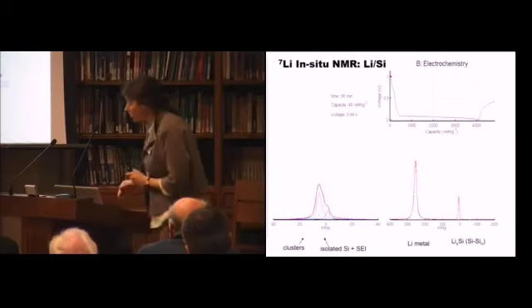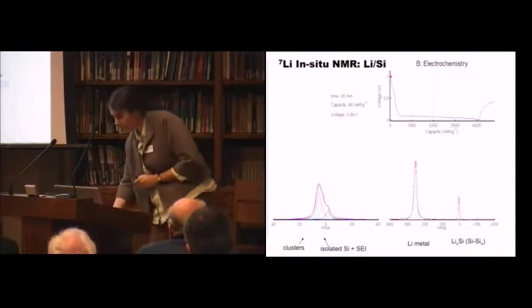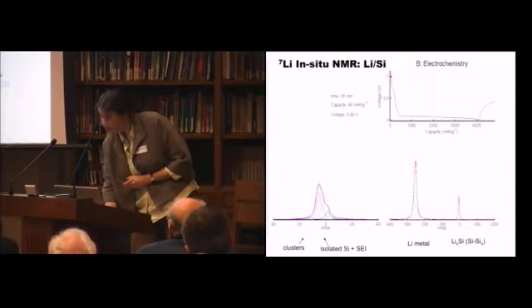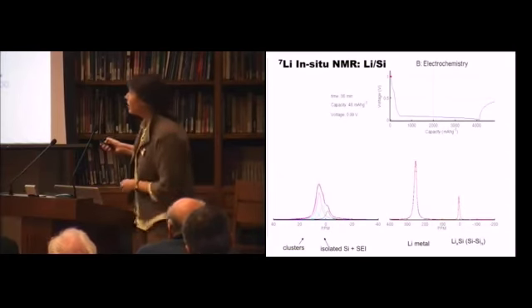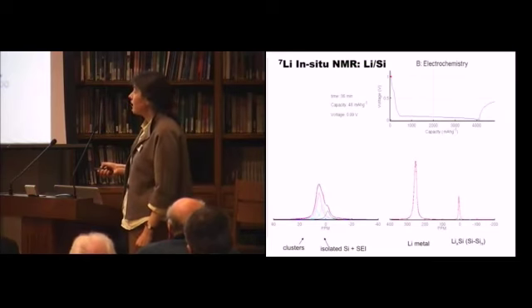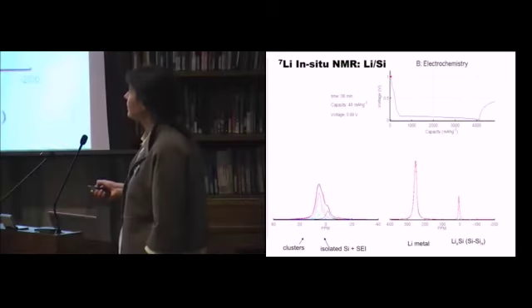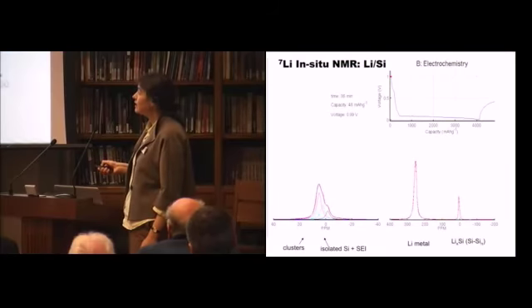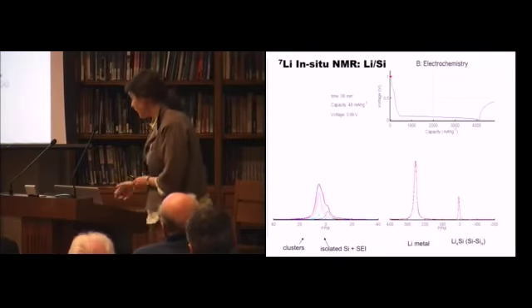And so this is a plot of the lithiums, assuming it works. Come on. Here's the electrochemistry going on, and you can see the formation of the clusters as you're lithiating the material. And then you can see the isolated ions, but you can also see this negative peak that comes and disappears.